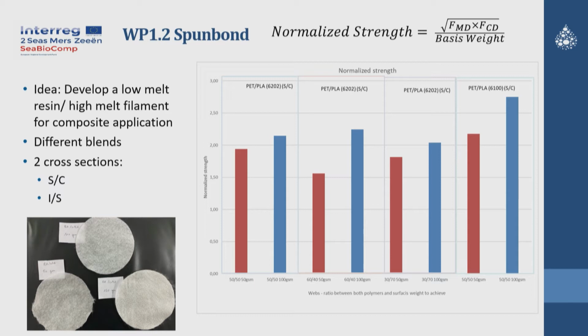What we observe is that, for instance, PLA chemistry could play a role, because you have two different PLAs used, 6202 or 6100, and you see clearly that there are some differences in tenacity, in normalized strength, sorry. Normalized strength is measured in both directions of the non-woven, and we normalize it so we see clearly the strength of the whole non-woven. This is the goal of the normalized strength. And we clearly see that the PLA polymer's chemical structure could play a role there.